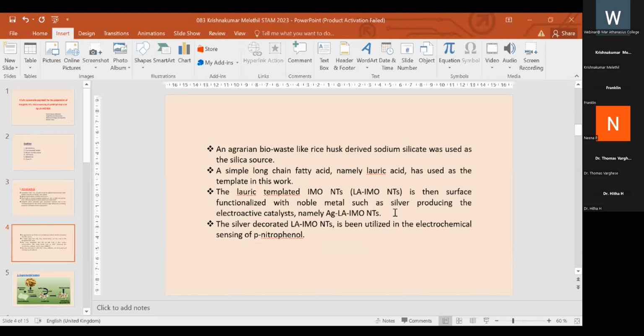In lab conditions, most are prepared from TEOS as the silica source, but here we used RHA, rice husk ash, as the silica source. After burning the rice husk ash at high temperature, we dissolve it in 3 molar sodium hydroxide and convert it to sodium silicate. Sodium silicate is the silica source, and we applied a naturally occurring fatty acid, lauric acid, as a template to help form imogolite nanotubes. It's a time-taking process, 3 to 10 days; here we treated for only 4 days.